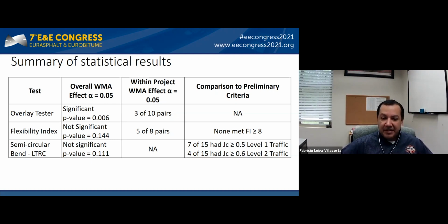And in the case of flexibility index, there was preliminary criteria. All of them failed that criteria. However, we were expecting that because those mixes had RAP and recycled asphalt shingles. So that was expected. And the last test was the semicircular bend test, and we didn't see any significant differences. And again, that was okay because we were hoping to have a similar or better performance. And a number of mixes were classified up to level 1 or level 2 traffic, not as good as the energy ratio results that we observed before, but at least we're observing that we can have some classified in high traffic or high volume.